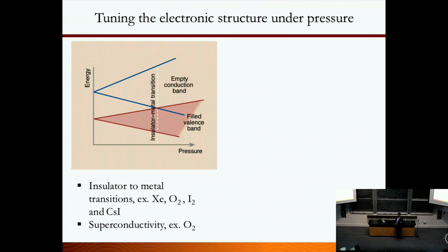So a noble gas can be a metal, and also you can make new bonds with noble gas and some other materials. Recently there was a paper, helium bonded with sodium. So different kinds of new bonding can happen. And oxygen, as I mentioned before, can go to a superconducting transition. This is one of the molecular superconductors that exists. And iodine goes to an insulator metal transition and becomes an atomic metal, and so does cesium iodide. So virtually you can think, if you subject every material to pressure, it can transform to a metal.